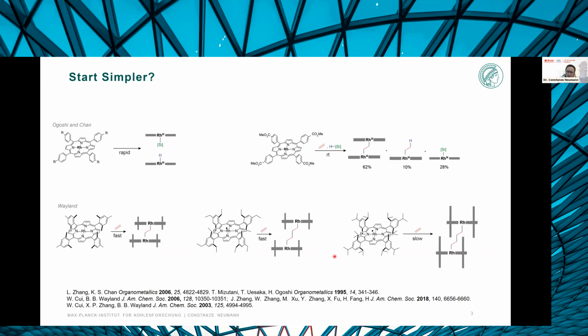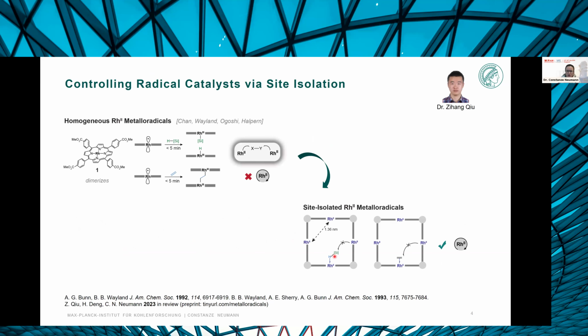So we thought that maybe instead of steric frustration, we have geometric frustration present in the MOF that would not allow the rhodium centers to actually react across the ethylene, so that they would have to engage with the substrates in a new and different fashion, which would hopefully allow us to develop catalysis. And the nice thing about the MOF is that despite the fact that we can no longer have any processes that involve 2 rhodium centers reacting across the ethylene molecule, there's still a high concentration of rhodium-2 sites present in the MOF.